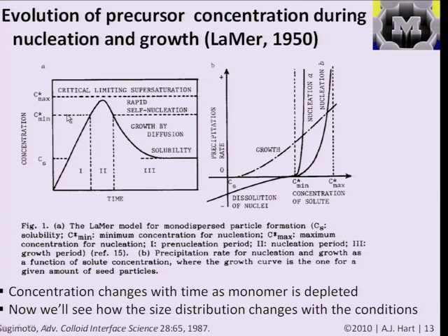So if we, for this one point, hold the idea that all the particles are the same size, then you're going to end up with particles that are exactly equal to the critical size, that won't grow or shrink in the solution because their size is in equilibrium with the surrounding concentration of the monomer. Clearly, you're not going to consume all the monomer or all the precursor, because then that would mean the particles would dissolve. So in the end case, you have some precursor left over, and you have some particles, and the particles are in equilibrium with their surroundings.